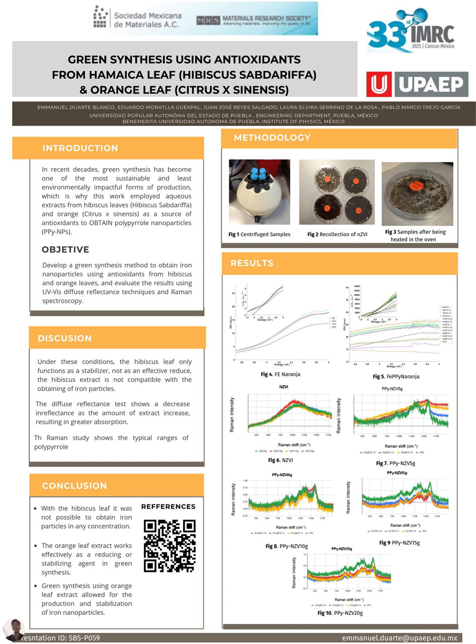In my examples, as the plant extract increases, the relative intensity of the band 1330 to 1318 centimeters minus 1 grows compared to that of 1580 to 1600 centimeters minus 1, and the peaks widen a bit. This indicates more doping, more charge carriers, and greater disorder, amorphization typical of doped nanopolymers. Sometimes the peaks shift a few centimeters minus 1, indicating that the components from the extract interact with the polypyrrole chain.